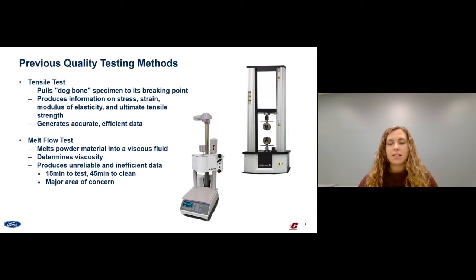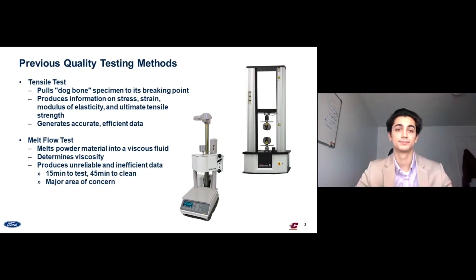Additionally, the melt flow test machine is very time consuming. It takes Ford team members up to an hour to complete. That's 15 minutes to test and 45 minutes to clean. Therefore, Ford came to us to find a new solution to their issue, and this test method can ensure consistent results when determining if the nylon 12 material is suitable for use.